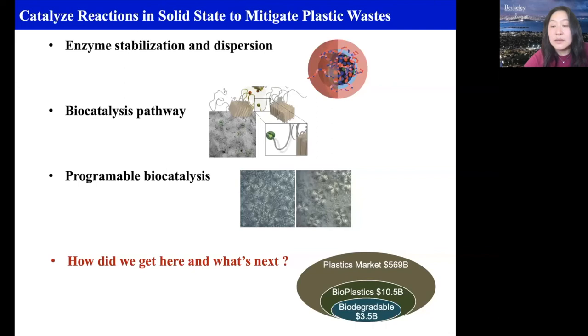We didn't want to look into degradation in the beginning because we think there's a reason why biology doesn't really degrade polyolefins. And as we looked more into it, we understood it's a way to protect ourselves, because the C-C bond and the C-H bond just so routinely exist in our body. And it was really satisfying to learn why they are not degrading that fast. But on the other hand, it really taught us some ways to potentially engineer programmable catalysts that allow us to modulate the process, to have on and off, to really get the best of both worlds. That means we can functionalize or control the fate of polyolefins, especially those piled up as waste, as well as try to avoid any potential harm done to our ecology and our environment.